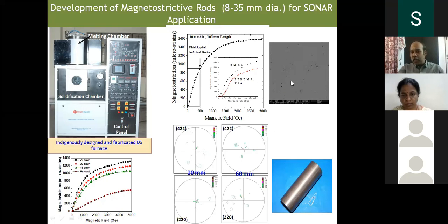The compositions are found to be homogeneously uniform, and the texture we found is the 112 texture, which is required. With this sample, the magnetostriction we measured was found to surpass the value that has been internationally reported. There is a company in the US, Etrema USA, which supplies this kind of material. The magnetostriction values we have achieved were found to be much superior to what has been supplied by Etrema also. So the material development program was very successful, and we were able to produce magnetostrictive rods up to 30 mm diameter and 80 mm long without any pores or defects.